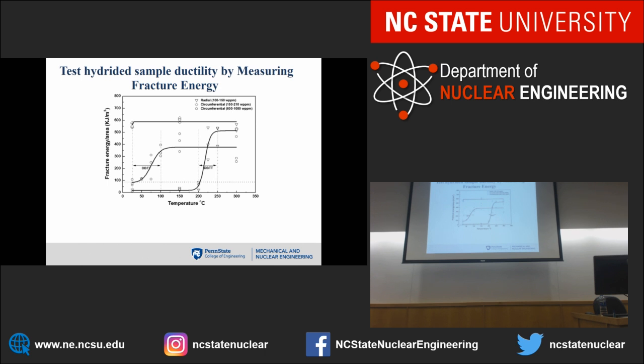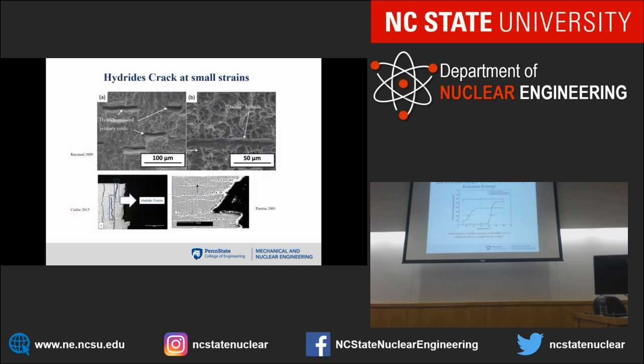for circumferential hydrides at low concentration, radial hydrides here. The ductile-brittle transition temperature. You know, you go from low energy, which is brittle, to high energy, which is ductile, and you go in a very small temperature range. About 20 degrees, you change from completely brittle to completely ductile, right? We don't know why this happens. But we do know that it tends to happen at a higher temperature, which means it's more dangerous than if you had lower, if you have circumferential hydrides. But we don't know what causes this, right?